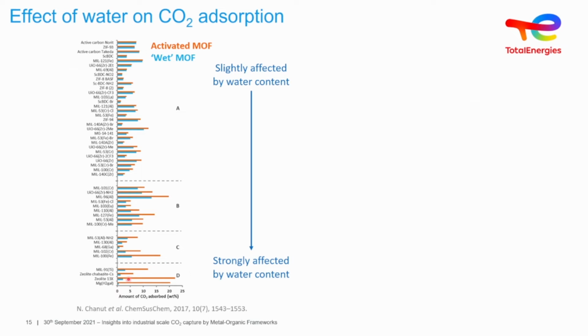And we can see here, of course, that we know that in many cases, zeolites, water adsorbs preferentially with respect to CO2, and we can see that our 13X is down in this last category of materials. We also can see that active carbon, many carbons are fairly hydrophobic, and so if they're put into the presence of water, maybe only a small amount of water is adsorbed, and so there's little effect. But what we can see is some materials in this category here and this category here could be of interest.